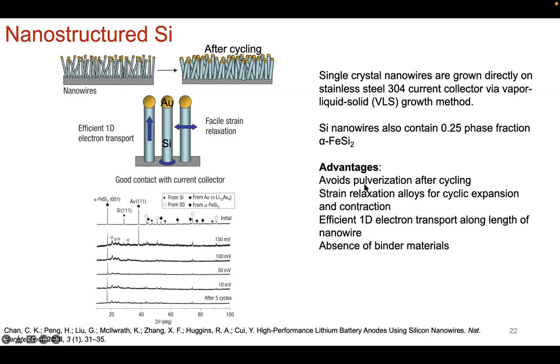And what's also really good about this material in terms of the advantages is that there's strain relaxation along the growth direction that survives the expansion and contraction over thousands of cycles. Okay. And on top of that, and this is a theme that we'll revisit, is the issue of the binder, right? If you have your active materials in particle form, what you need now is to make a composite where you have continuity, right? You need to have your active material, that's silicon or sulfur, that's electronically insulating, be in contact with that of a conductive carbon, and then all of that needs to be bound together via a polymeric binder, which, at the end of the day, adds weight to your electrode design, right? And eventually your cell. That's no surprise there.